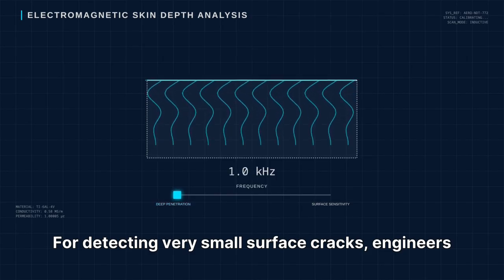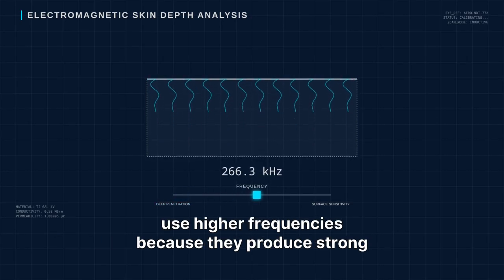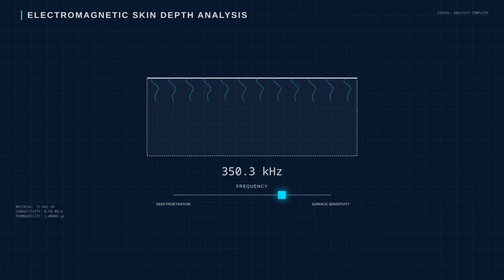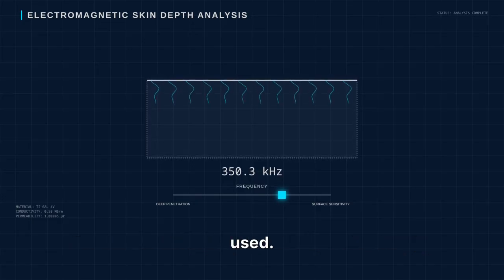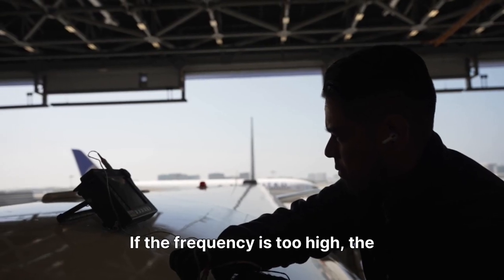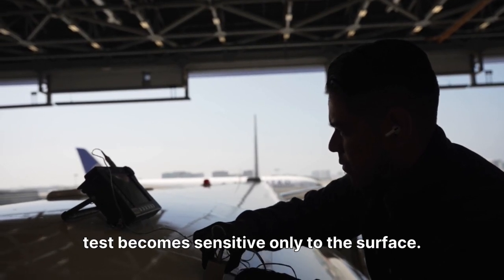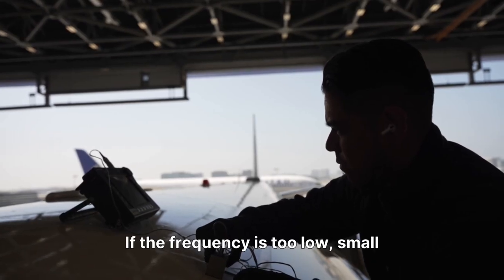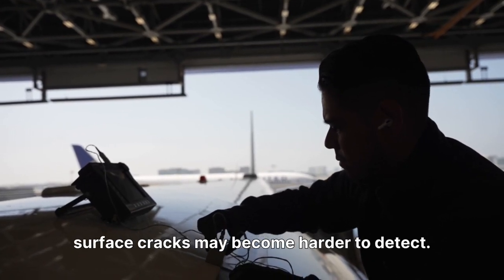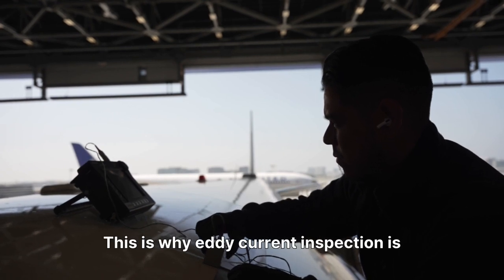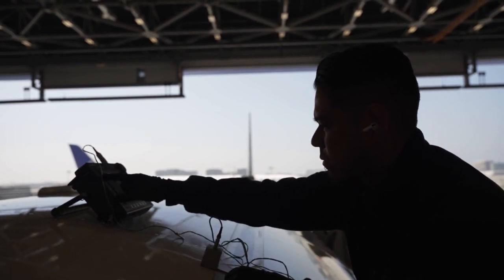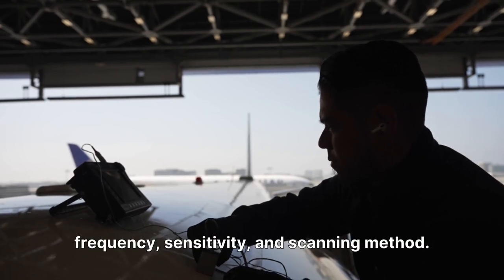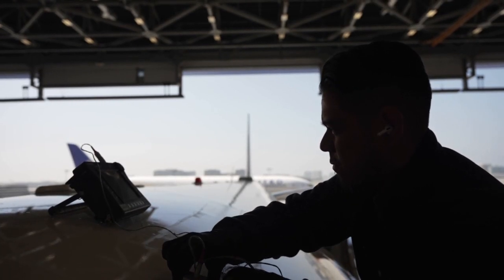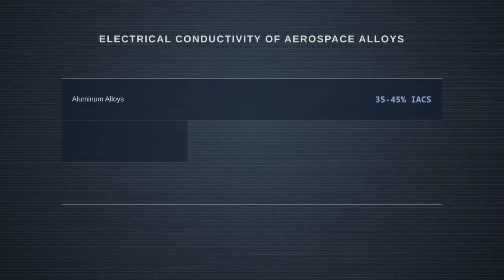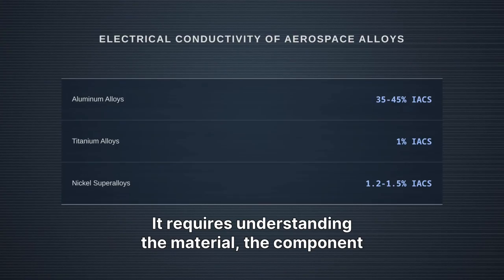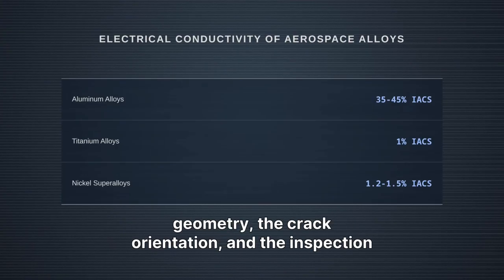For detecting very small surface cracks, engineers use higher frequencies because they produce strong surface sensitivity. For deeper defects, lower frequencies may be used. But there is always a balance. If the frequency is too high, the test becomes sensitive only to the surface. If the frequency is too low, small surface cracks may become harder to detect. This is why eddy current inspection is both science and skill. The engineer must select the right probe, frequency, sensitivity, and scanning method. Aerospace inspection is not just pressing a button. It requires understanding the material, the component geometry, the crack orientation, and the inspection objective.